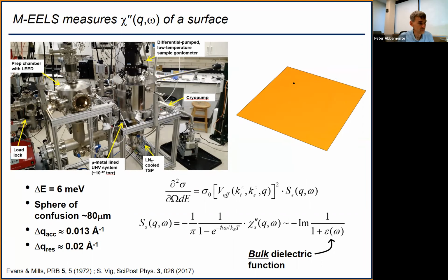there's an approximation that works very well, which is called the distorted wave Born approximation. I know there's neutron people who do this too. So this whole expression and these matrix elements come out of the distorted wave Born approximation. Basically you say, I don't have a plane wave in and a plane wave out. What I have is a plane wave reflecting off the surface with some reflection coefficient, and that's my incident wave. And then the final state is another combination of incident and an outgoing wave.